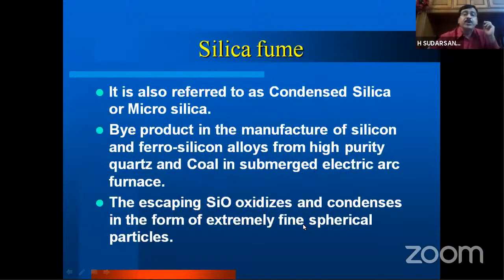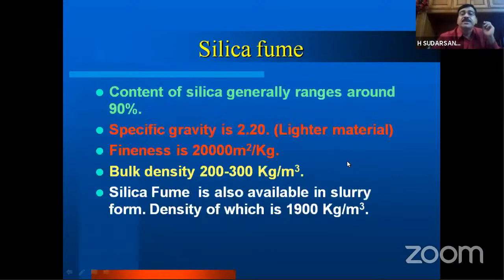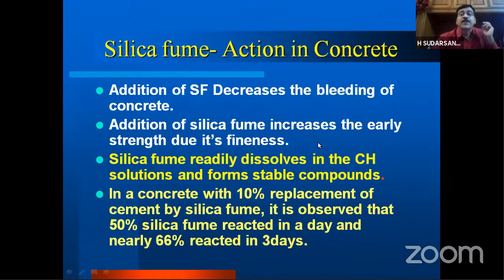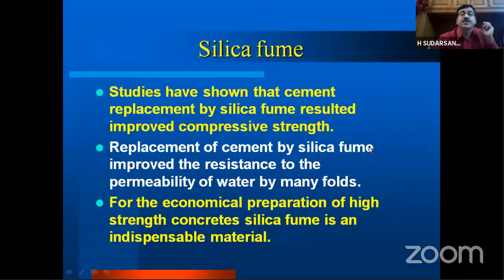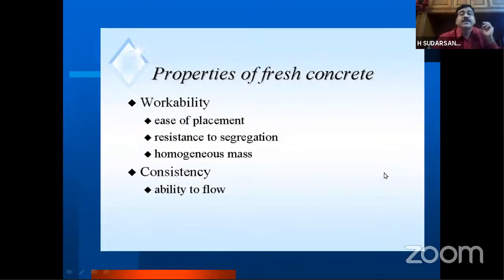Similarly, silica fume is a byproduct in the manufacture of silicon and ferrosilicon alloy industries. It is a product that comes from quartz. It has a very huge surface area, so it's a wonderful mineral admixture. I'm just skipping all these because of lack of time. It has a specific gravity of around 2.2, and you can see the fineness is 20,000 square meter per kg. It's a very high surface area if you test the silica fume by Blaine's apparatus. So silica fume acts in different ways in concrete and improves the durability.